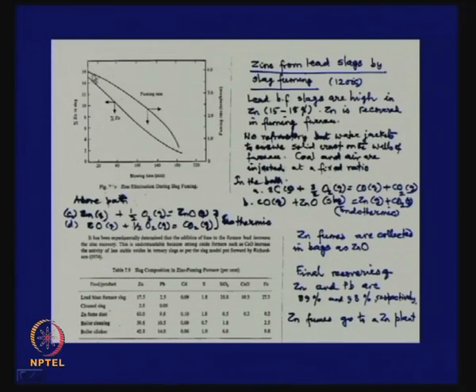Whereas, the fuming rate, the rate at which zinc is coming out, which is shown on this side, initially would be high, but with blowing time gradually the fuming rate will drop because there is not enough zinc oxide left in the slag. So, typically we need in minutes say 120 to 140 minutes to come somewhere here, and about 180 minutes, about 3 hours of blowing of carbon and oxygen to recover most of the zinc oxide from the slag phase. That is where the fuming rate becomes very low.